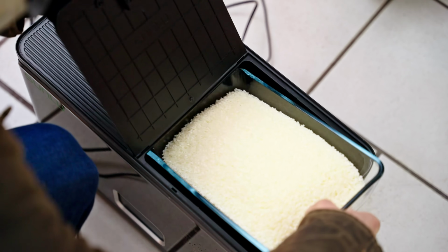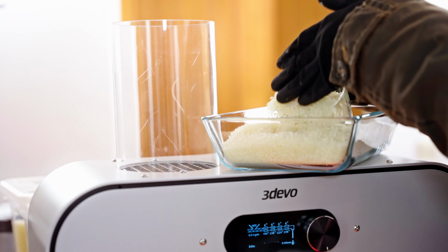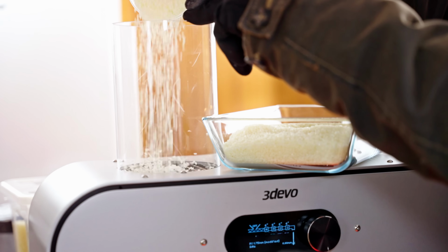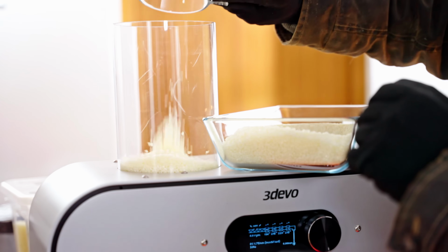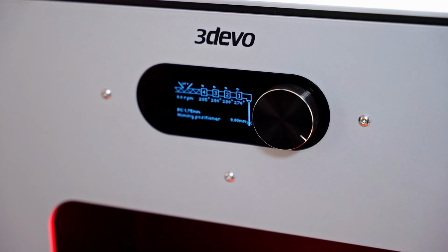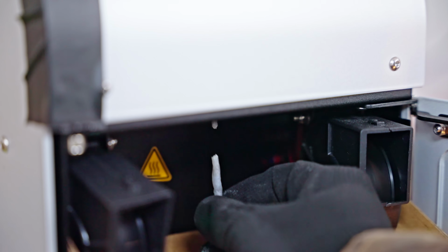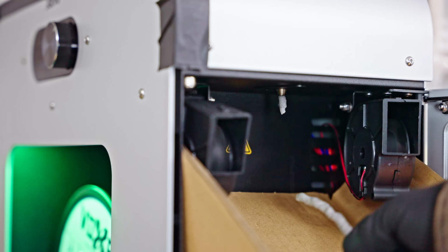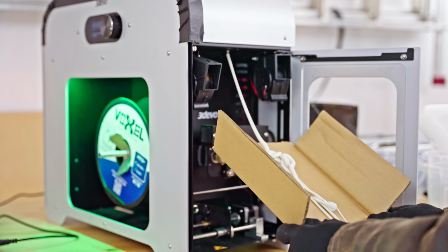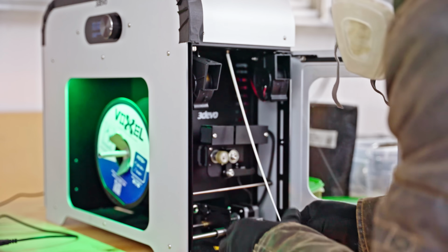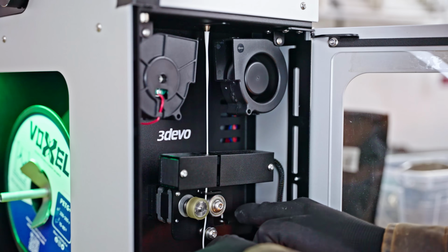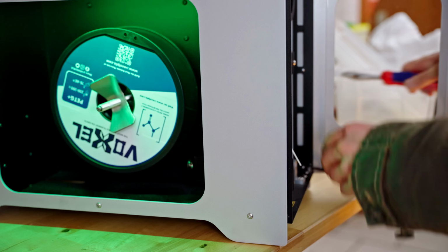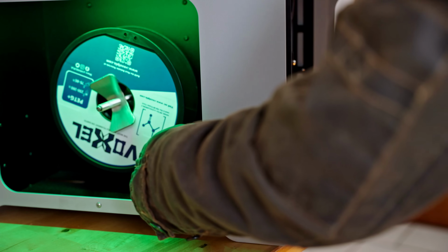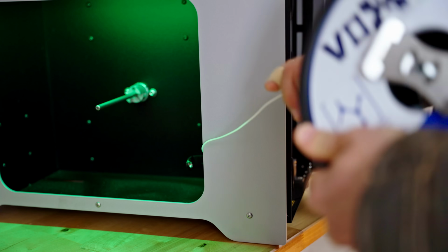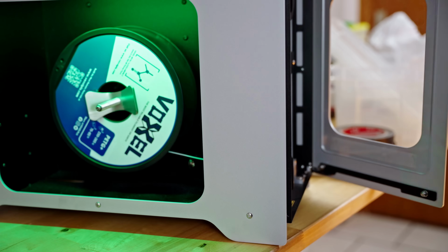I learned from the last time that I was making filament, and this time I had the polycarbonate blend resin in the dryer for about 12 hours, so this stuff should be as dry as it gets. I started by tuning in the extrusion parameters for just the pure base material, and I learned that I would need to go way lower in extrusion temperature than what the preset was on the 3devo filament maker, because this is not pure polycarbonate, it is a mix of different materials that is easier to process. And eventually, I had managed to extrude about 50 grams of the base material with a very consistent diameter.